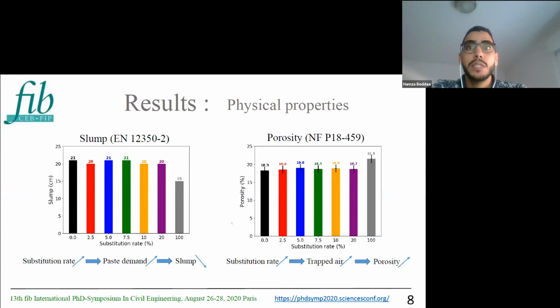So concerning the porosity accessible to water, the results show that the porosity remains unchanged for the substitutions lower than 20%, but for a total substitution, we can see a significant increase in the porosity. This result can be explained by the fact that up to 20% of substitution, the air trapped by the shells is negligible compared to the porosity of the overall concrete, while the total substitution of the coarse aggregate by shells makes this effect and this porosity much more pronounced.